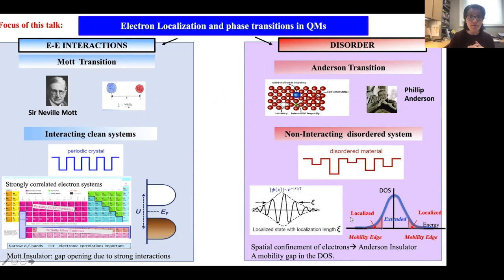So let me give you a very quick overview of what type of electron localization I'm going to look at in this talk. Generally speaking, if you don't break translational symmetry, electron localization can be driven by two routes: electron-electron interaction, which we often refer to as Mott transition or Mott-Hubbard localization, and it happens in clean systems, but usually in materials which feature very strong electron-electron correlation. These materials represent a big chunk of our periodic table. These are systems with partially filled d and f orbitals, and this Mott insulating behavior is characterized by the opening of a gap in the density of states.